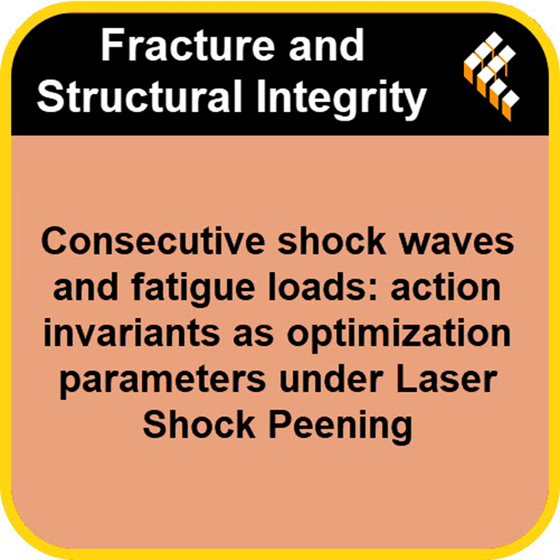The optimized shock input, informed by the action invariant concept, fundamentally boosted the material's resistance. So bringing it all together, the path forward isn't just about applying LSP and hoping for the best based on residual stress. It's about optimization using these deeper physical principles. The goal is to use the two invariants, one from the shock and one related to fatigue, to set up a formal optimization problem. Like a mathematical equation to find the perfect treatment. Essentially, yes. It's framed as a minimax problem. You want to find the shock parameters, the pulse amplitude and duration, that maximize the subsequent fatigue crack propagation time under the expected service loads.